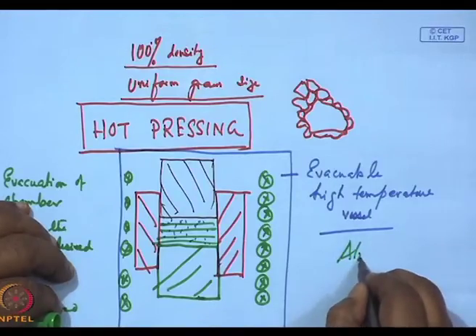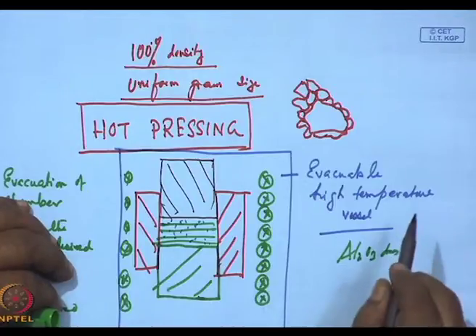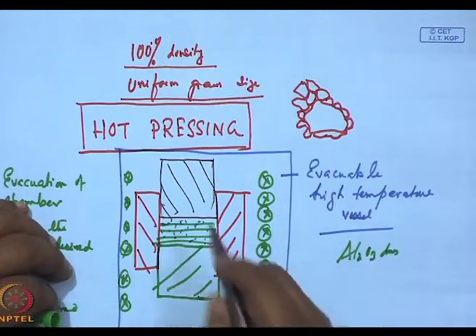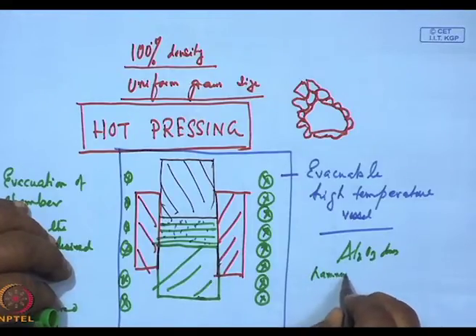So, one problem is the thermal mismatch problem of the die, the anvil, the hammer and the pellet, a matter of serious concern. And unless one can really address this problem, hot pressing will be very difficult. However, people have got sintered alumina disc simply by using alumina die, hammer and anvil.